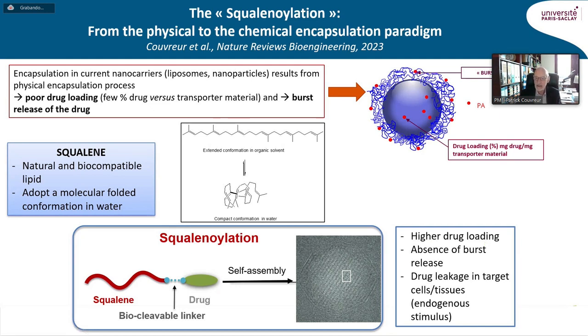a physical encapsulation process, just because, as you can see here in this cartoon, each molecule of the squalene will be able to transport at least one molecule of the drug. And also you will have an absence of burst release just because you have a chemical link here in blue between the drug from one side and the squalene from the other side.